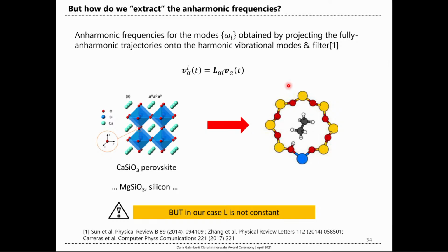Then you have a molecule, for example C2H6, ethane, that has these CH3 groups that can rotate with large amplitude motion relative to each other. Then the molecule during your simulation can be attached, but can detach, then attach again, can turn around, can rotate. And so you can see that in our case, the assumption that this L matrix is constant in time is a bad approximation, it cannot be true.